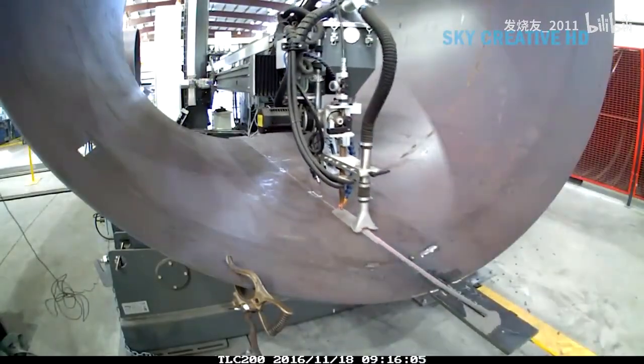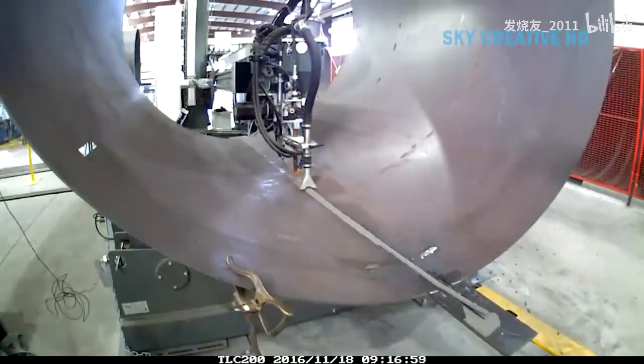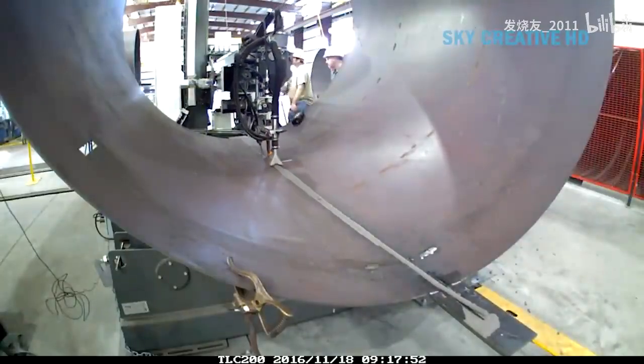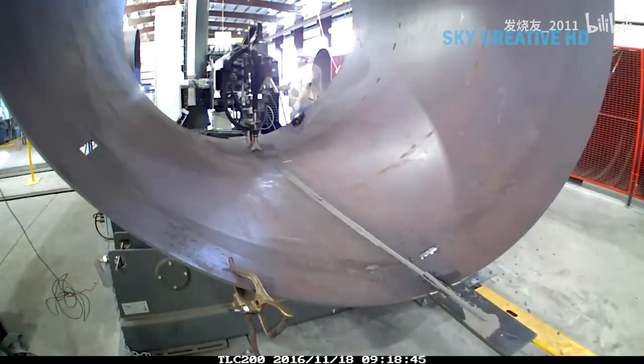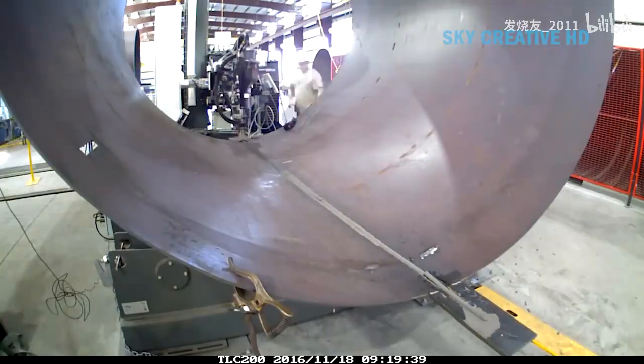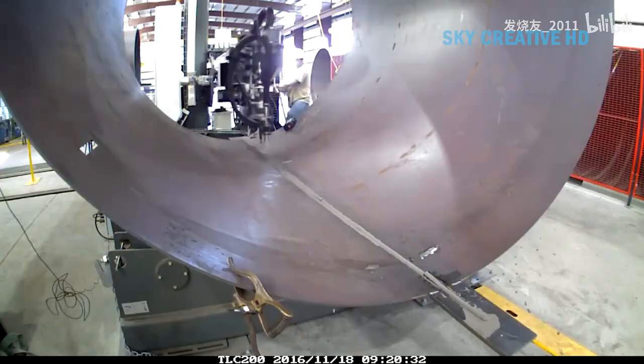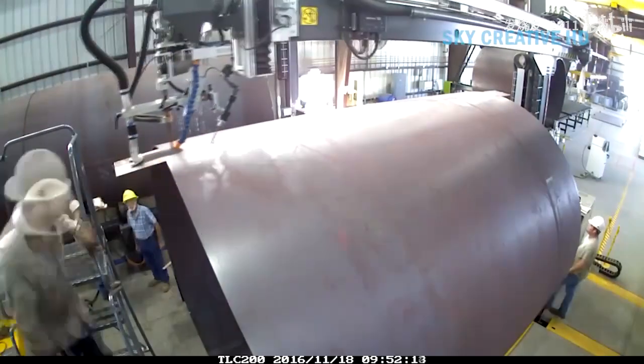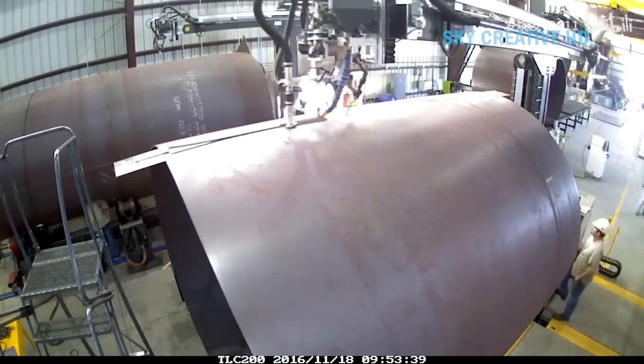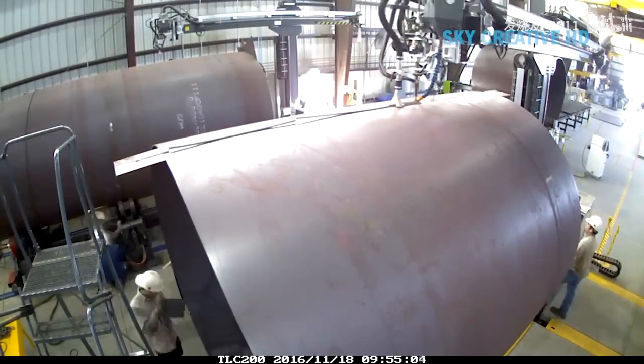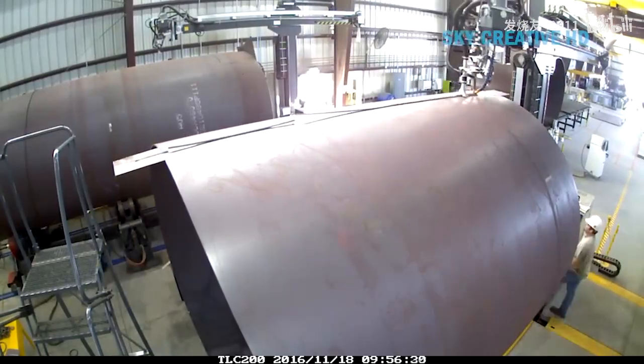The welding process truly demonstrates the craftsmanship. Submerged arc welding is usually used for the main welds in tank manufacturing. The arc runs under a layer of granular flux, protecting the weld from atmospheric contamination, while achieving deep penetration and high deposition rates. Whether flat, concave, or hemispherical, the heads will be installed and welded.